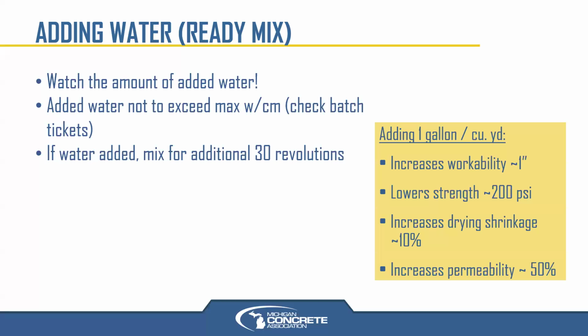Okay, so you're going to get a strength reduction. You're going to get increased drying shrinkage, because that water isn't actually needed in the concrete. It's just going to evaporate at some point, leaving a void behind, and the concrete's going to want to shrink because of that change in volume. So increased chance of cracking is something that additional shrinkage can cause.